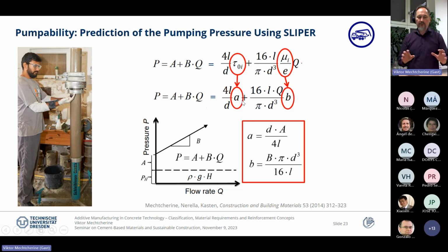All right. So from Sliper, we can derive A and B, small here, like material parameters, and then put them in the equation where we use not the length of the pipe in Sliper, but the real length and real diameter of the pipe. We get this equation, and then we get a relationship. We can really predict the pressure depending on the flow rate in the pipe. So this is essential for predicting the movement of concrete in the pipe. And of course, there are some other issues with blockages, etc., but I will not address them today.